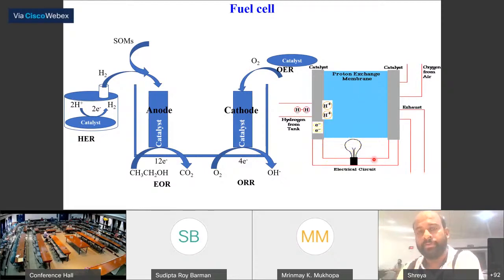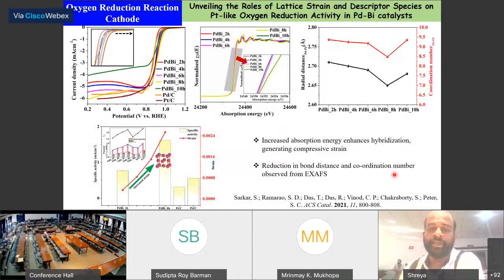technology we are developing in the lab: we develop electrode materials for anode and cathode, for oxidation and reduction reactions respectively. One such example, just one month back, we published in ACS Catalysis. What we have done here is synthesize a palladium 3 bismuth catalyst and mill it for different time periods in a ball miller, at 2 hours, 4 hours, 6 hours, 8 hours and 10 hours.